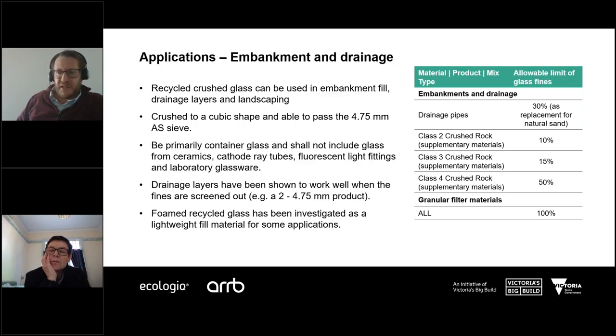So embankment fill, you would think, represents a very large opportunity to use recycled crushed glass due to the sheer volumes of material that are used in those applications. We've seen recently that there's been a number of local government entities that have been introducing recycled crushed glass as drainage layers within their pavement structures. So typically they've been screening their recycled crushed glass product, taking a product that would be within 2 to 4.75 millimeters, which is seen to be free draining, and allows us to produce drainage layers which could be used potentially above the subgrade in the pavement structure.